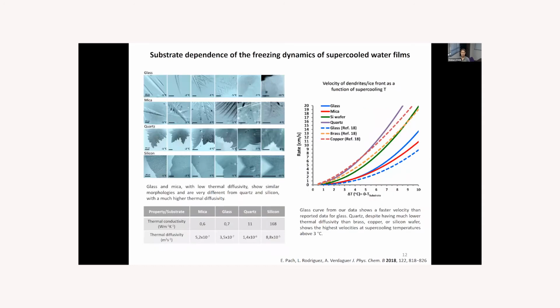So here you can see the optical microscopy images of different surfaces, glass, mica, quartz, and silicon, with lowering of the supercooling of water from -1 degrees to -10 degrees. We have used the sharp ice tip to induce the nucleation at each temperature. And you can see that the glass and the mica with lower thermal diffusivity show similar morphologies.